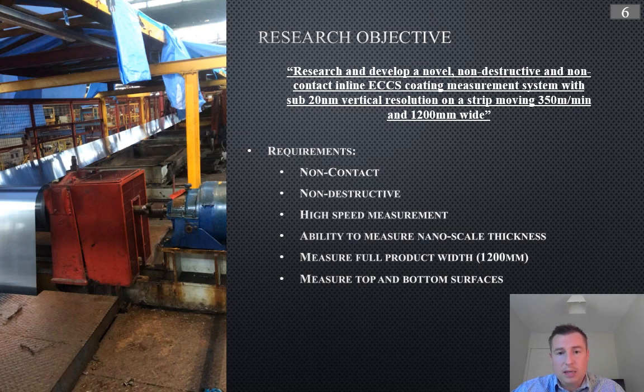So a few of these requirements came up in the initial meetings. This system has to be non-contact, non-destructive. It has to be able to measure with high speed because the product's moving so fast on the production line. It has to be able to measure these nanometer scale coatings, measure the full product width, and measure the top and bottom surface coatings.